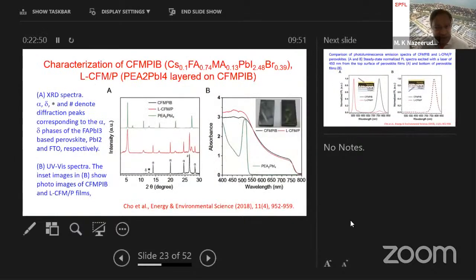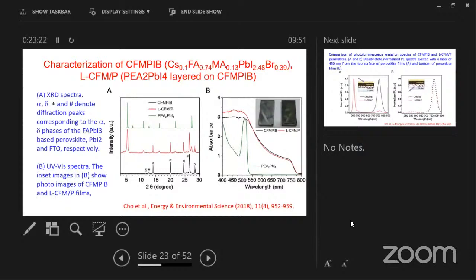I'm showing you the characterization techniques of these materials, putting two-dimensional perovskite on the top of three-dimensional perovskites. So before I go, let me just give you the composition. Here C is cesium, F is formamidinium, M is methylammonium, P is lead, iodide, and bromide. This is the composition of our perovskite, and the constituent amounts are given here. Now we put the layered perovskite.